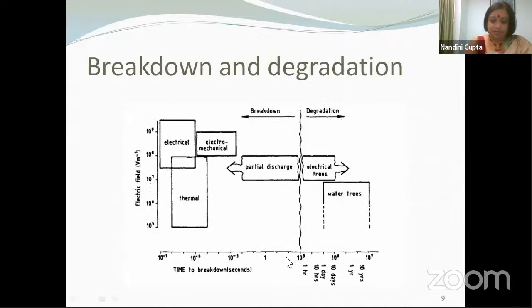So here I have a figure which is taken from Dissado's book on aging. What you see here is we have two clear-cut divisions between two processes. On the left, we have the breakdown processes. And what are the various breakdown processes? Electrical, electromechanical, thermal, and partial discharges. Partial discharges are not instantaneous processes. So you see electrical, thermal, or electromechanical processes will lead to breakdown in seconds or less than seconds. But partial discharges will take a long time to cause the material to progress to breakdown. So these are the breakdown mechanisms, and when we design an insulation, we automatically take into account that these are the processes which may cause catastrophic failure. So we have to make sure that they do not happen.